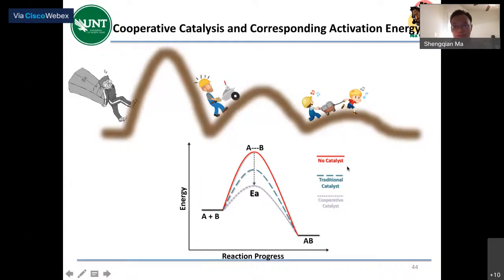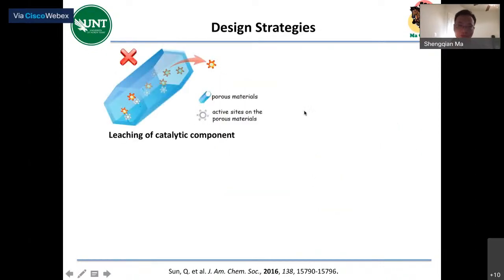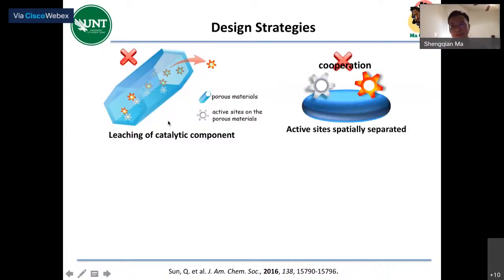One of the features, of course, is cooperative catalysis. How to design the cooperative catalyst, right? Of course, there is a lot of research going on. We can put some co-catalyst in the pore, in the molecular catalyst, and incorporate some active site on the pore. But the shortcoming is, during the catalysis process, they're going to leach, particularly in solution, right? And the other way, a lot of research going on is for surface catalysis. They precisely place two active sites on the surface and it allows them to cooperate.